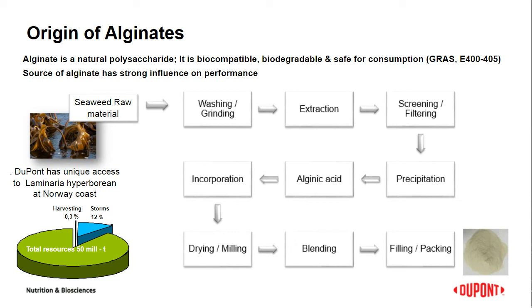First of all, the source of the brown seaweed has decisive influence on the final chemical composition and therefore on the applied performance of the alginate. As the nutrition and bioscience business of DuPont, we have unique access to Laminaria hyperborea on the west coast of Norway, which enables us to deliver alginate products with high gel strength. Only 0.3% of the quantity of the seaweed is harvested in a 5-year cycle, which allows us to deliver sustainable products. The harvested seaweeds are first ground to 5 to 10 millimeter square pieces.